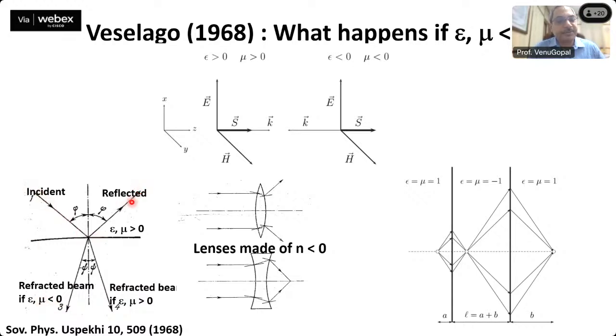So he showed that the reflected wave has no change. Your incident angle is phi, your reflected angle is phi, it remains the same. However, the refracted beam is towards the normal in the case of an ordinary material, but in the case of an extraordinary, negative index material, it is away from the interface. So the angle is minus phi instead of phi. A consequence of this is that if a lens is made of a negative index material, instead of focusing, a collimated beam falling on it will get diverged. And a concave lens made of an n less than 0 material works as a focusing lens.